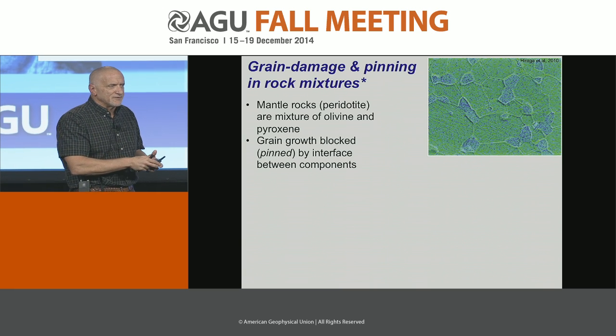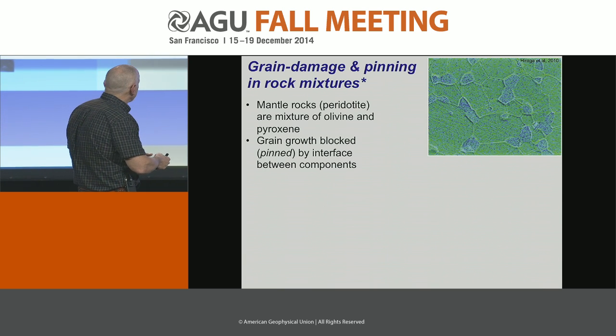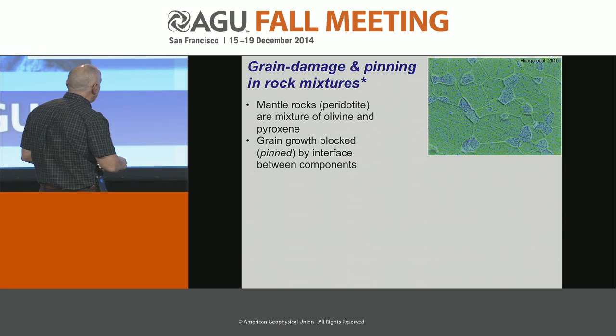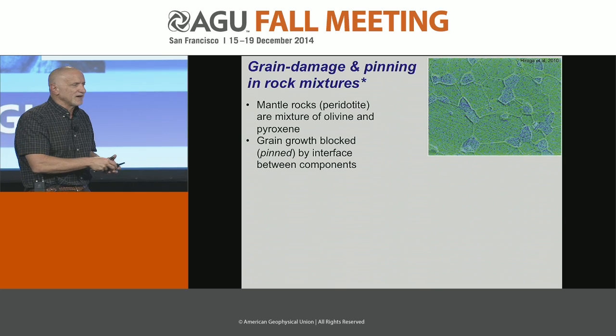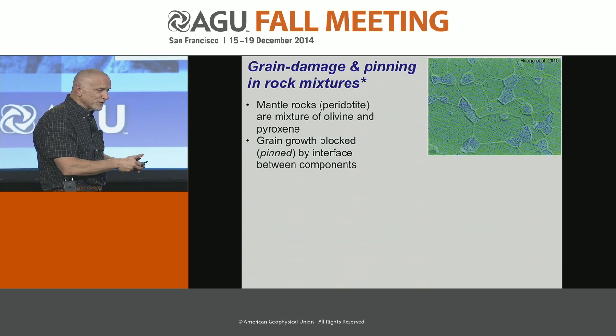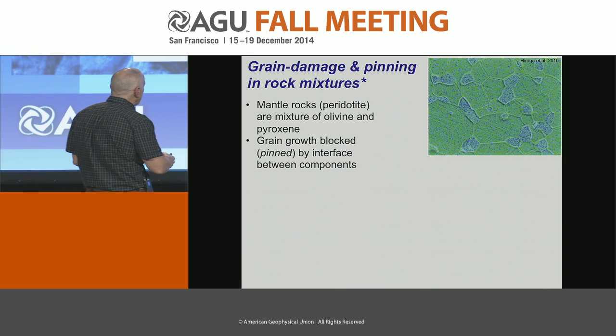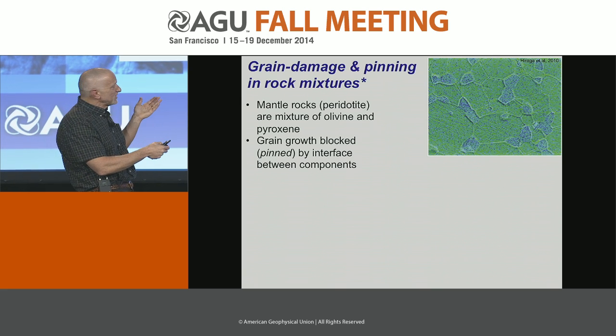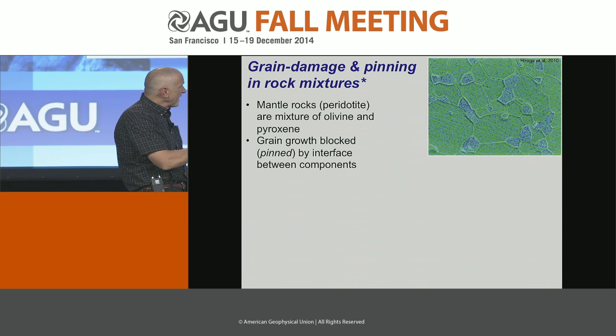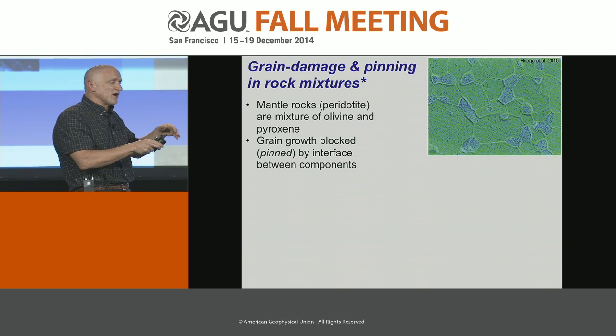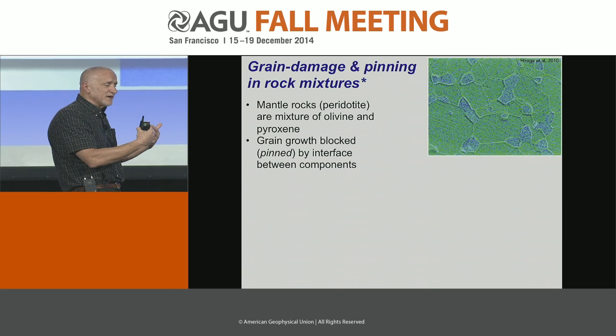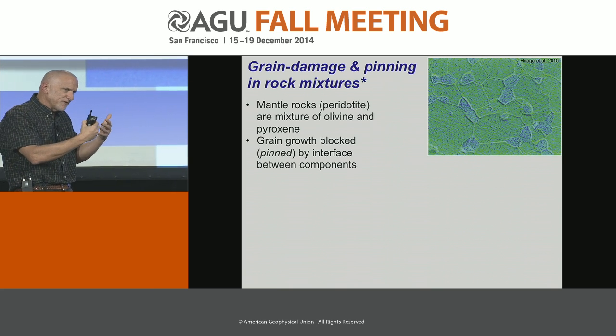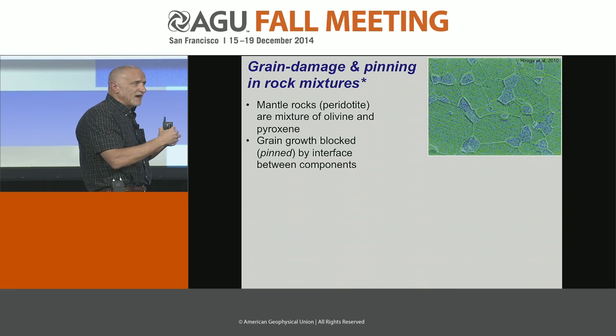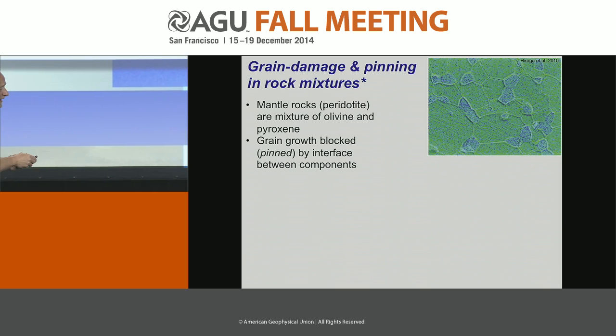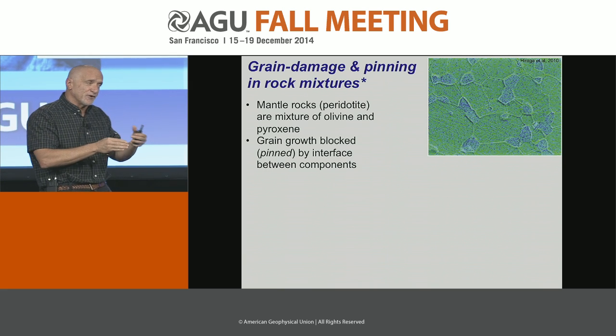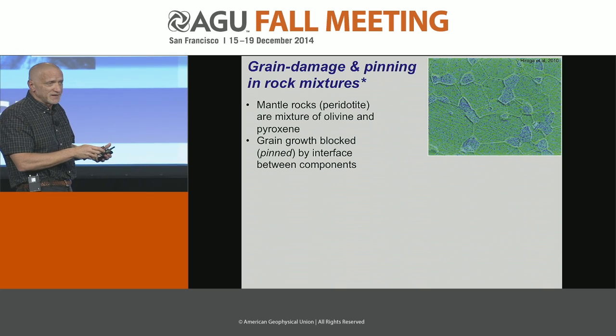Well, real rocks, of course, are not just simple olivines, they're mixtures. At least, in my simple-minded view, they're mixtures, in a mantle peridotite, of olivine and pyroxene. I mean, various forms of pyroxene, but I'll keep it simple. My olivine and pyroxenes are either green or blue. So the grain growth, in this particular case, in a mixed system, tends to be blocked. As a big olivine tries to grow and runs into a grain of pyroxene, its growth is blocked, because if it tries to engulf that other grain, it goes to more surface energy by becoming more distorted, having more protrusions in it as it tries to engulf this other grain, which is a higher energy state, which is not preferred. So it will shut down grain growth, and this is a thing called Zener pinning.